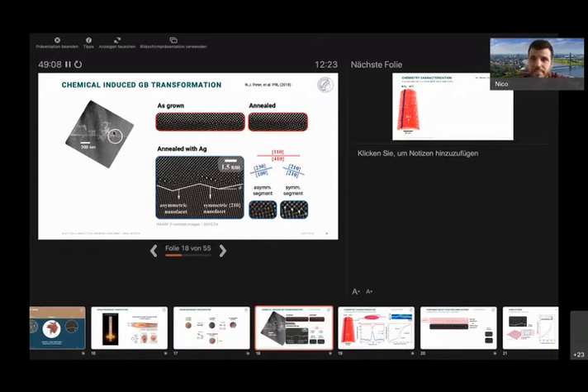I see. Okay, Jaya, is it okay for me to ask the last question? Yes, please go ahead. Okay. So it is still not clear why they segregate, because there could be interfacial energy arguments that having silver on certain boundaries lowers energy. There could be interface stress arguments that this 2D grain boundary is having a different elastic property. So it is softer, for example, then it can undergo an instability like ATG, because your last movie was more like that, it's undergoing buckling. And it is also possible that because of elastic strains that come from the size differences, there is this kind of breaking up of the boundary that is happening. So what is the basis of this sort of breakup?